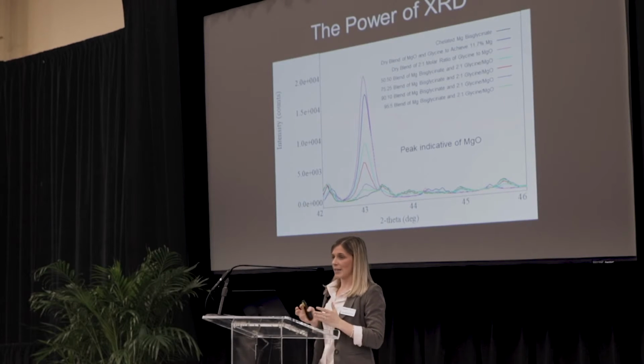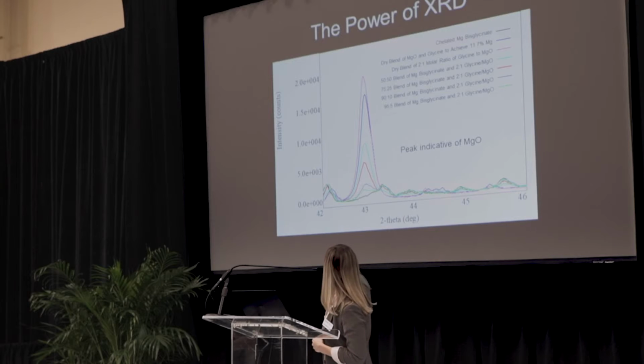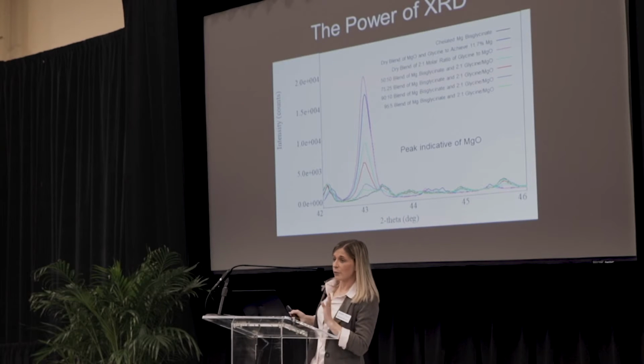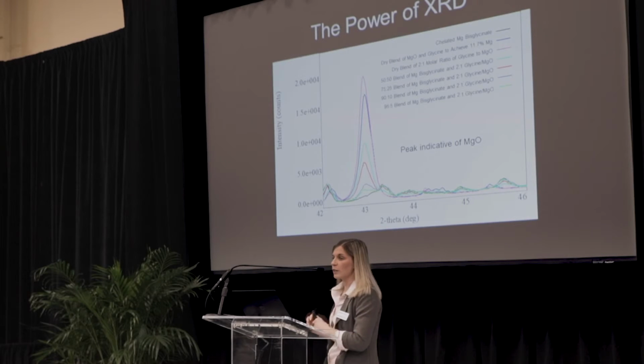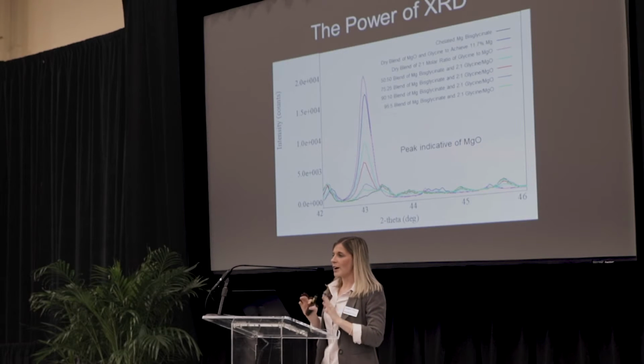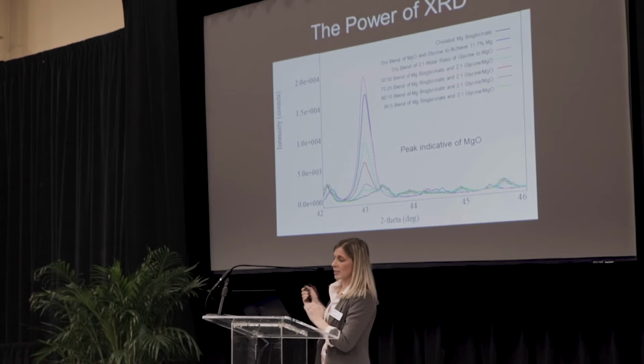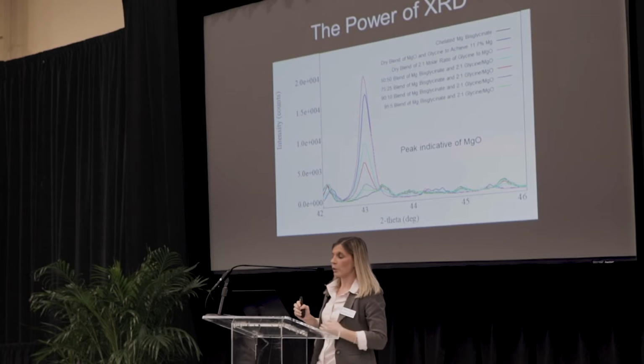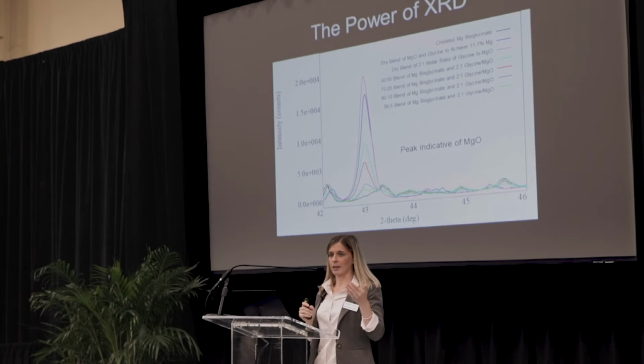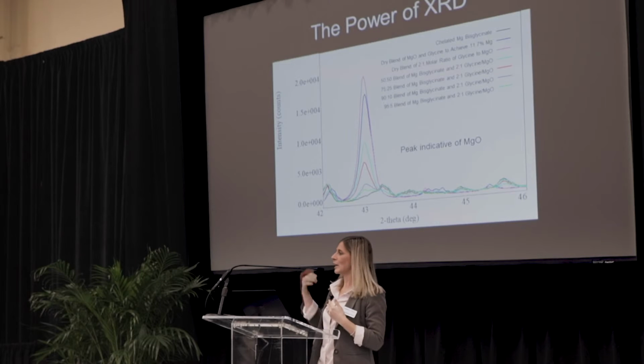What you can see is that the black data is the fully chelated magnesium bisglycinate. I'm showing you then a peak that's indicative of magnesium oxide. As you can see for the black data, it's completely flat in that region. Then we took our 95% reacted sample, so it's only 5% unreacted. And this is the lime green data, and you can already start to see a peak right there. For the 90% reacted sample, the peak gets a little bit bigger. For the 75% reacted sample, it gets even bigger. And you can see the trend here, that we can really detect even in tiny quantities if there's unreacted magnesium oxide or glycine present in these samples.